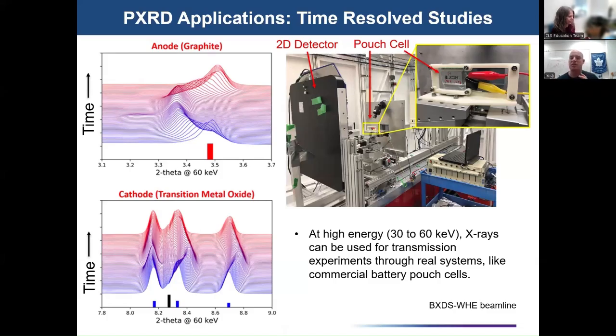But with synchrotron X-rays at really high energy, you can perform transmission measurements on real battery systems, like the battery pouch cell that's shown here. You can measure how peaks shift during battery cycling to better understand how the materials are behaving while the battery is actually operating.